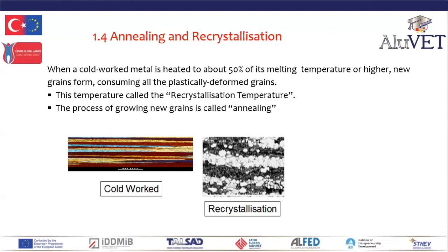So annealing, the growth of new grains, is a function of the degree of cold work, the temperature, and time. The greater the degree of cold work, the faster the annealing rate. The higher the temperature, the faster the annealing rate. So when we anneal a metal, we take it up to a temperature approximately half the melting temperature, hold it on time, and new grains start to grow from the old cold worked grains. With time, completely brand new grains regrow from the old grains, and we term this process annealing. And annealing is a time and temperature function.